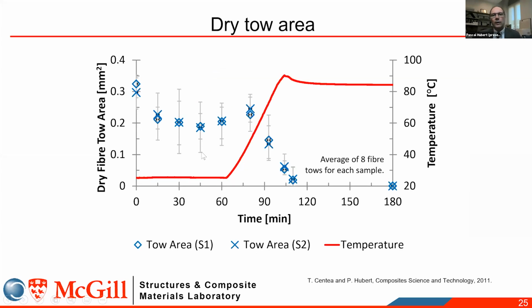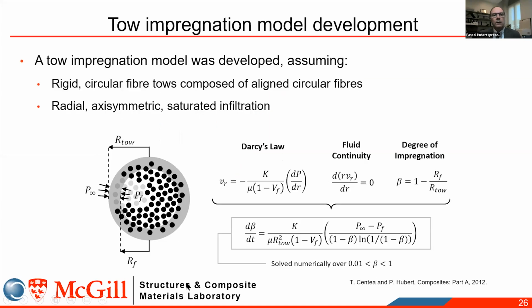So obviously there's some variability, but you can see the clear trend that those dry toes are initially quite large, but then as resin flows, it starts to come to zero. Now, through these great images, we can come up with a very simple model of the toe impregnation process by just assuming the toe to be a circular bundle that we surround with resin, and we just solve for the radial flow of the resin through the porous media.